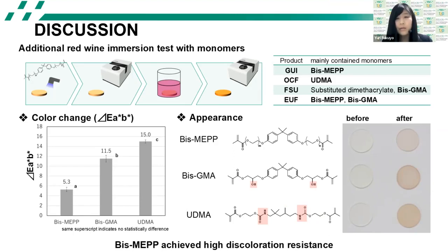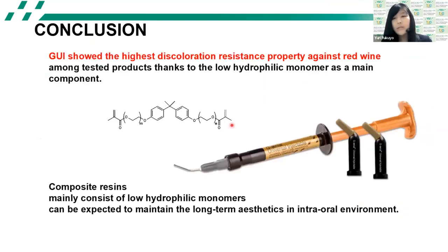Then in conclusion, GUI showed the highest discoloration resistance against red wine among the tested products. And it's thanks to the low hydrophilic monomer as a main component. And finally, it was concluded that composite resins mainly consisting of low hydrophilic monomers can be expected to maintain long-term aesthetics in the intraoral environment.